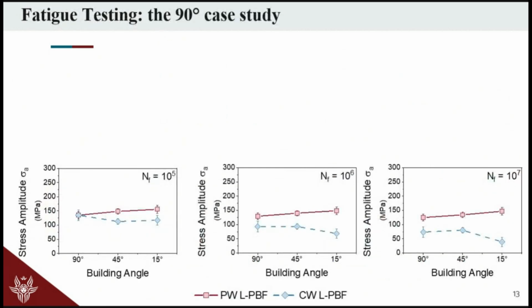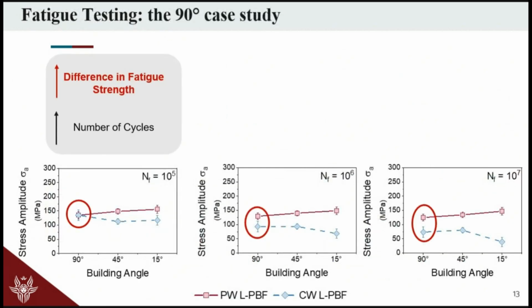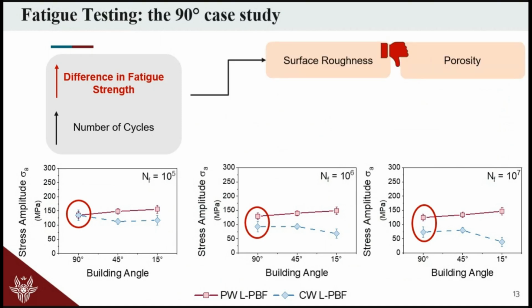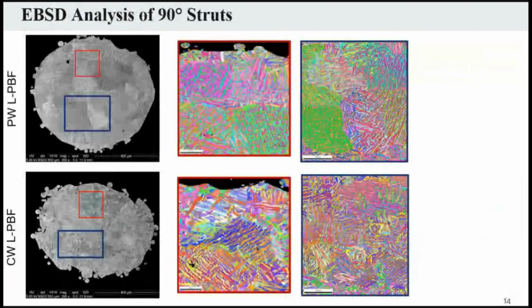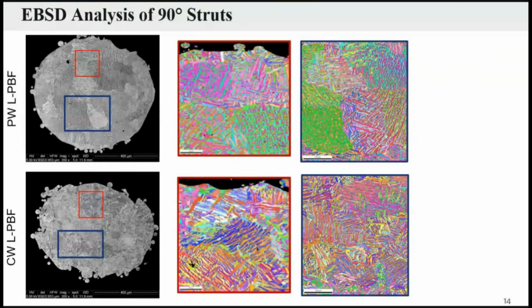In this case, if we look at the 90 degrees case study, as I said, there is an increase in the fatigue strength difference with an increase of the numbers of cycles. And this cannot be explained neither by the surface roughness analysis, neither by the porosity. So mostly probable, it's related to the microstructure. How did we deal with that? We did some EBSD analysis of the 90 degree struts, and we checked basically the overall morphology.